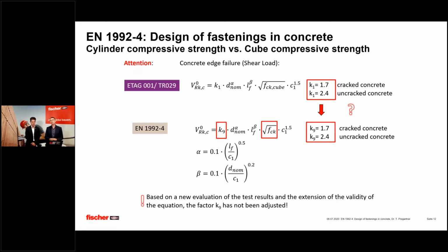Now, why is that? That is because during the development and the work on the new standard, EN 1992-4, they decided to reevaluate and reassess this complete failure mode. First of all, to make this conversion to the new compressive strength, but also to broaden the scope of the equation to larger embedment depth and in some parts also larger diameters. And with that, they still found that these two factors, 1.7 and 2.4, match the best the results of the tests and the finite element simulations that were the basis of the scientific work for this equation.